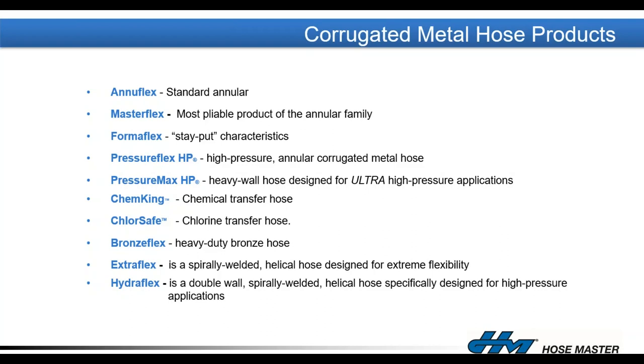If you have corrosive applications, we can make our Annuflex hose out of a special alloy that's a member of the Hastelloy family. It's a C-276 alloy, and that's what we call our ChemKing hose for general chemical transfer applications. Sour gas, sour crude, aggressive chemical applications, chlorine-containing chemicals, sulfur-containing chemicals would be applications where that ChemKing can be used. We sell ChemKing to an oil refinery that was optimized to handle sour crude in its refining operations, and they were having corrosion problems with their 300 series stainless steel hoses until they switched over to our ChemKing product.